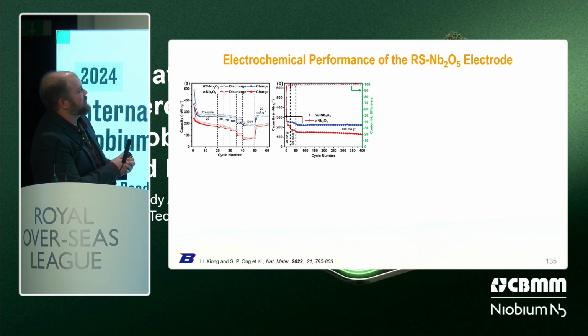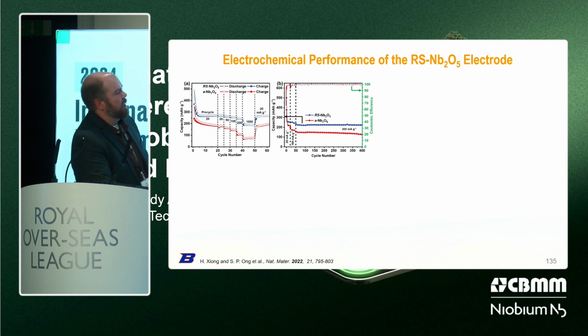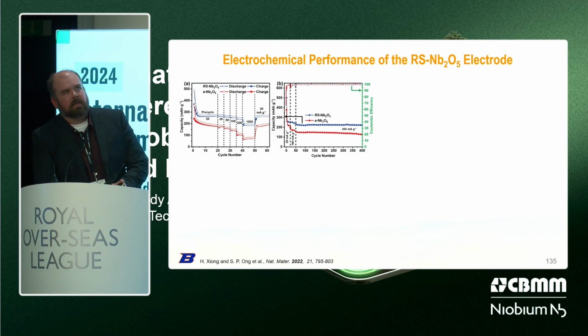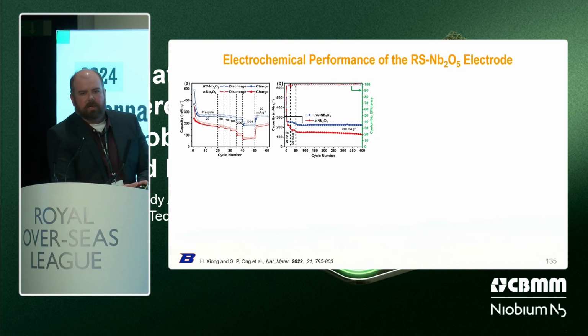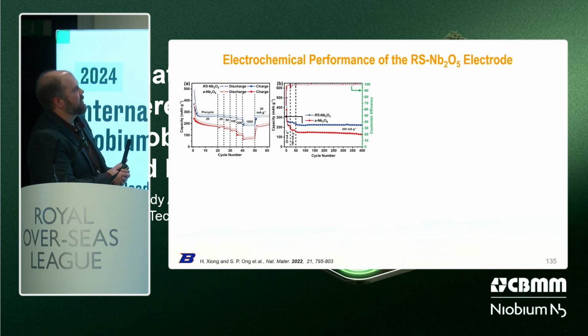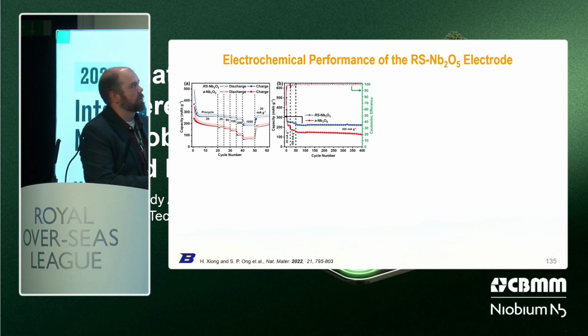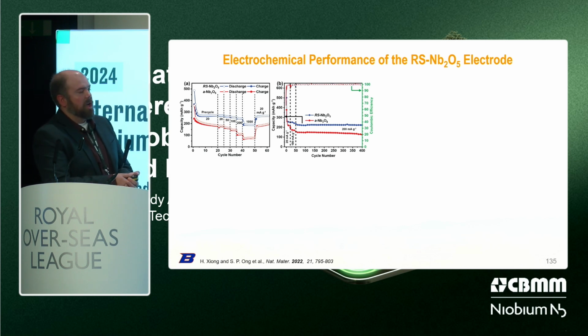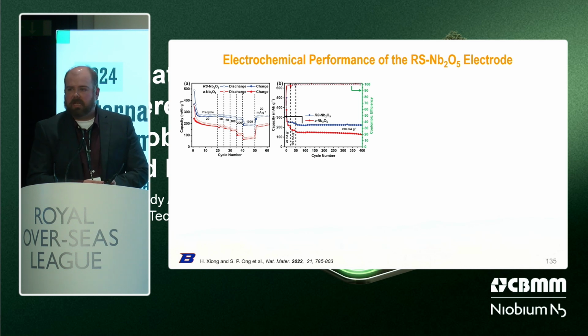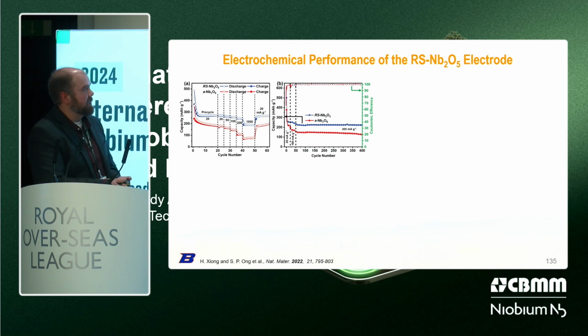And you can see here, the rock salt material is really stable, right? I'm going to actually jump over here. It's really, really stable. Over 400 cycles, we saw, I can't remember the exact number, I think it was 99.3 or 99.93. It's quite great. But on the rate capability side, we see that once we get to about 200 milliamp per gram, we're seeing a dramatic increase in the amount of capacity that can be contained in the rock salt structure rather than the amorphous structure. So there's obviously less impedance that is happening in the cell while it's happening at fast rates.